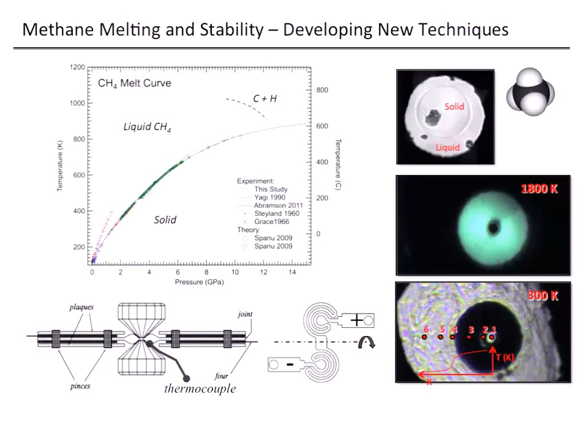We can do spectroscopy and measure temperature by means of pyrometry right at that spot. This black spot you see is actually the field of view of the pyrometer. And we can generate a uniform temperature distribution around the sample where we're actually making the measurement.